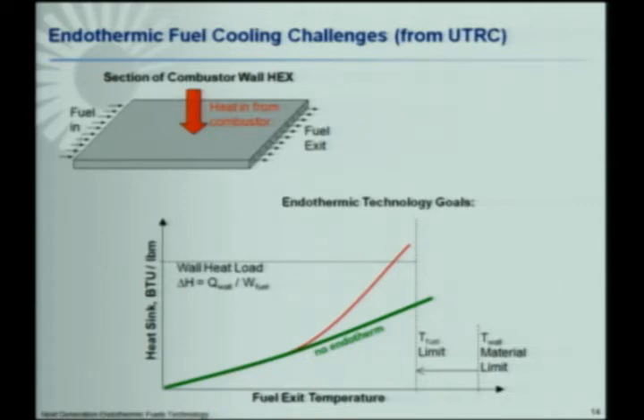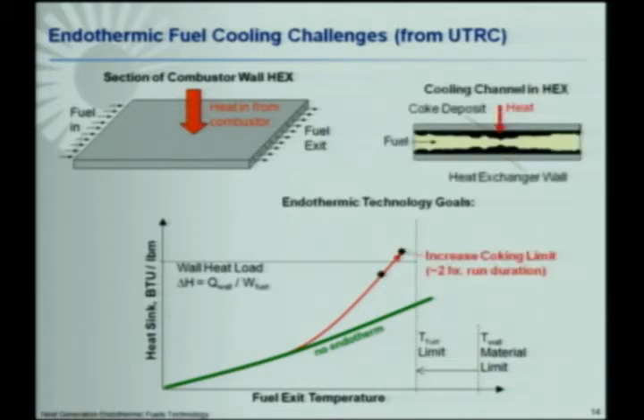So we've had some endothermic fuels, but they tend to clog up. They've put catalysts on the walls to catalyze some of these reactions. And over time, coke or carbon starts forming up. It starts clogging up these systems. Then it gets plugged up, and then you kind of lose that part of the fuel system. So you'd like to avoid coke deposition to increase the limit. If you could then induce other endothermic chemistry to crack the hydrocarbons in there, you could get additional heat sink to enable future missions.